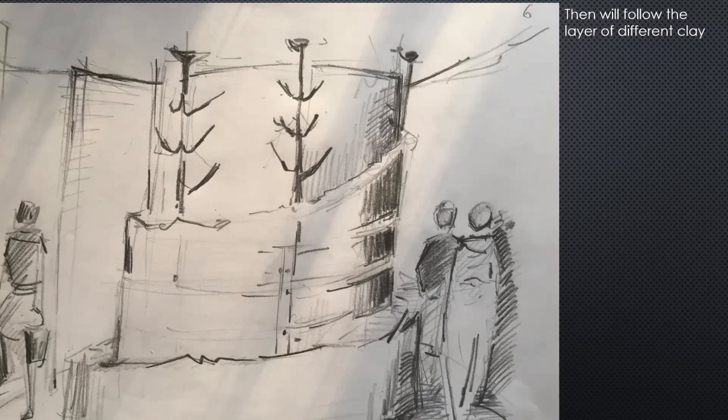The distance holders were pushed into this layer and connected the outer layer with the core material. They prevented the core from shifting when the wax was molten out. In our workshop, they were made of iron. A third layer of clay with fine split and straw ensured the stability. It was applied by hand, which is why it often shows fingerprints, maybe also the fingerprint of Phidias.